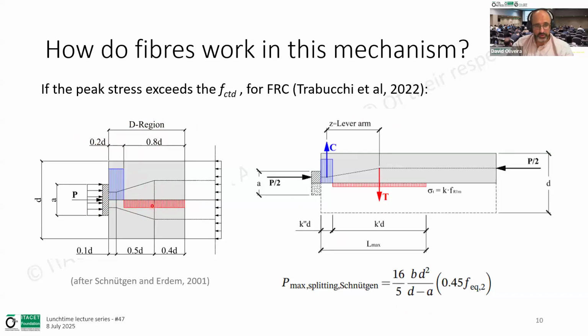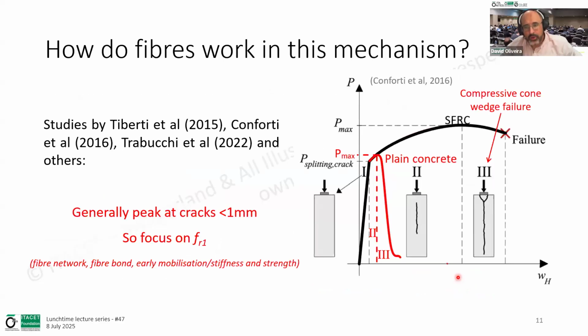And then Trabucchi, based on this model here, presented an estimate of the maximal force that we could apply for this joint based on Schnütgen, which could be calculated by this equation here, with this being a residual flexural strength that's converted to an equivalent axial tensile strength. Also, continuing with these studies, even earlier than Trabucchi in 2022, there are other works by a few other Italians, Tiberti and Conforti. They all studied how we can better understand the failure under highly concentrated loads and splitting, particularly splitting when we're using fibers.